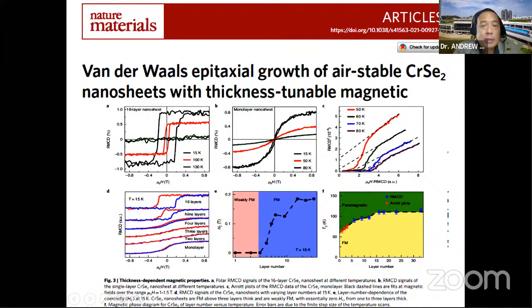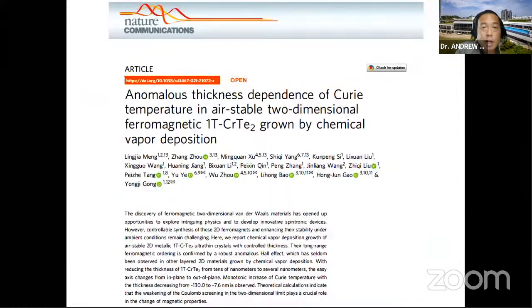Here's another paper, specifically on chromium ditelluride, which is the same material that we have grown, and the paper was just published. This time they showed that the 2D chromium ditelluride is air stable, right? And it's metallic. And they did measurements of the anomalous Hall effect to show magnetism.